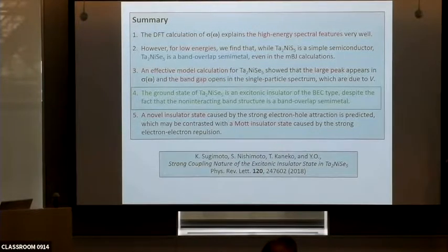What does that mean? I'm lost here. Okay, the problem is that the non-interacting band dispersion is an assumption. We do not observe this non-interacting band. This is a hypothetical concept. But if we assume that the band structure is semi-metallic, then interaction gives you this insulating state, BCS-type exciton condensation. That is the assumption here. If we assume this, then we can explain